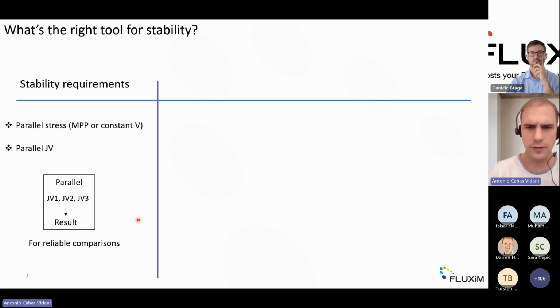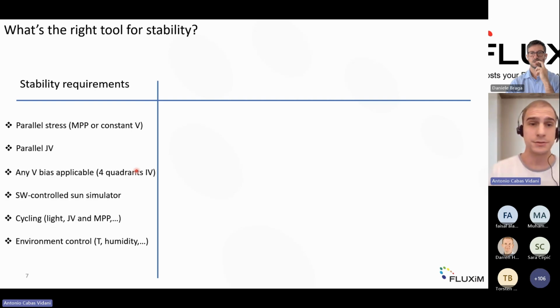This is why the tool that you are going to consider for your stressing experiments should manage to do parallel stressing. So this means all pixels are stressed at once, and also parallel JV. In this way, you can both have stressing conditions and characterization. As I mentioned, this is a key factor in the protocol. Stressing on its own is not sufficient. In addition to that, you also want the possibility to apply any sort of bias, which means positive, negative bias. Same goes for the current.